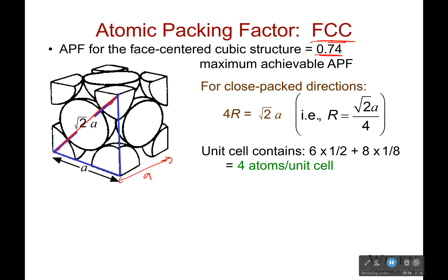So we can figure out the length of this line. That would simply be a squared plus a squared is equal to c squared. And that's what I'm trying to solve for. This is c. Two a squared is equal to c squared. And I take a square root of it. And I get a square root of two times a is equal to c. So that's where that length comes from.